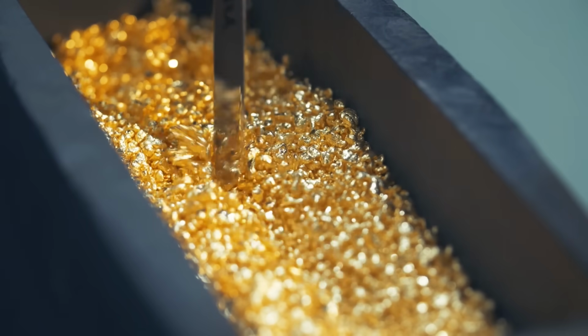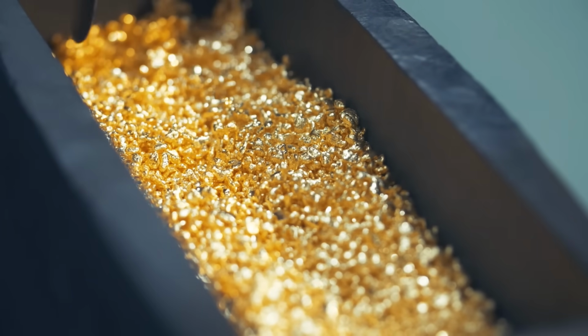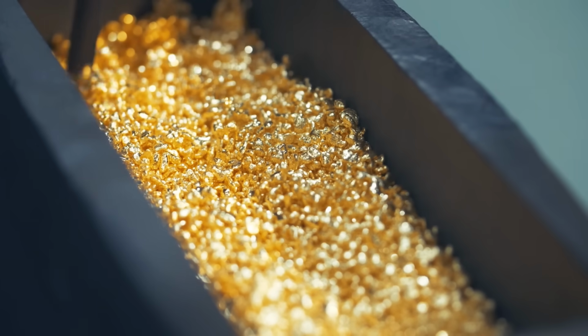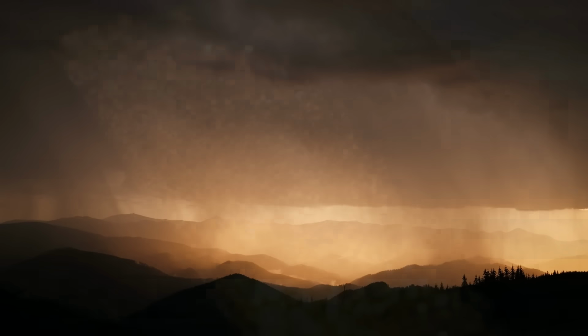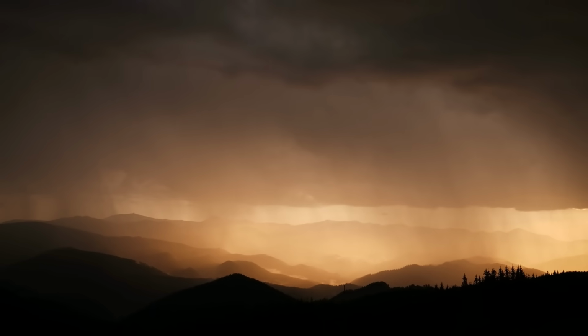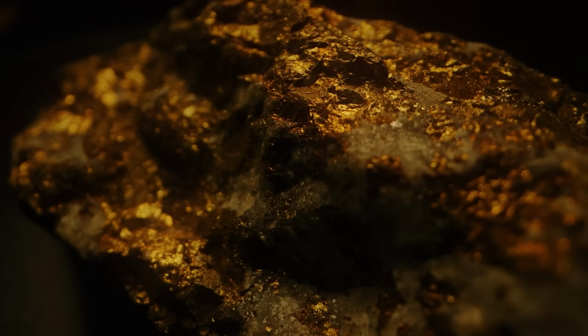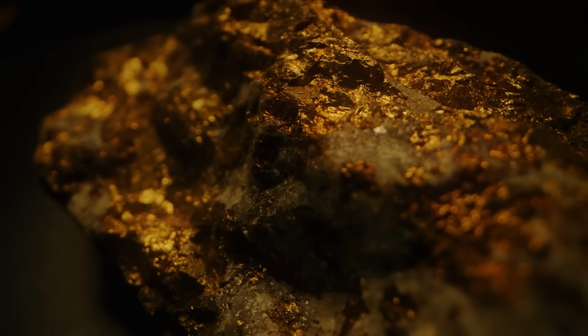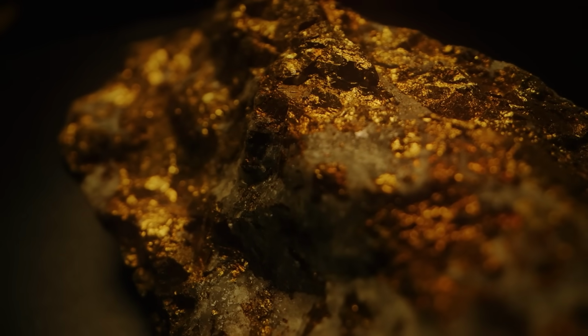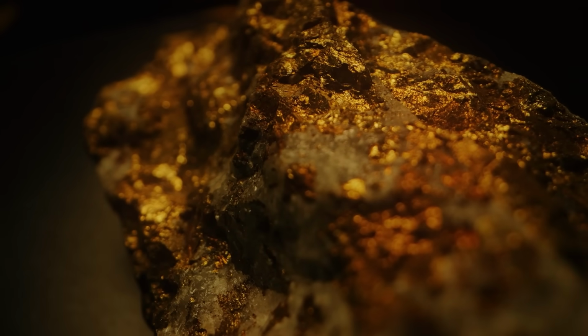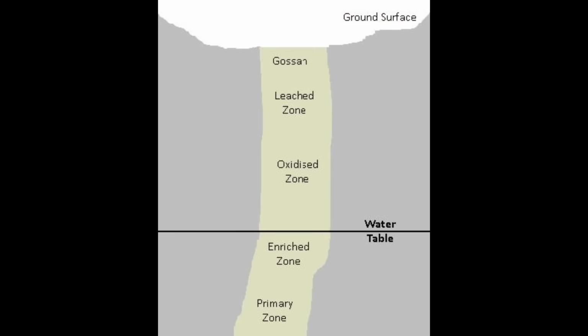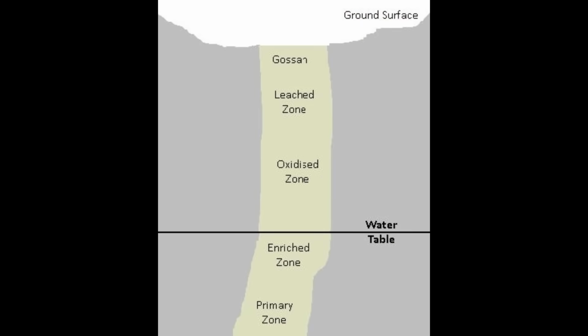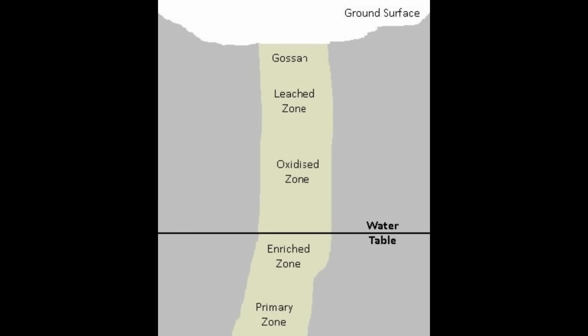And the gold? It survives. Gold doesn't oxidize under these conditions. It doesn't dissolve easily in these surface environments. So when the sulfide host is destroyed, the gold is left behind, liberated, no longer trapped inside a crystal lattice. It becomes free, sometimes as fine particles, sometimes reprecipitated slightly downslope, sometimes concentrated into pockets where fluid slowed down. This is what makes the oxidation zone so powerful. It transforms invisible gold into recoverable gold.